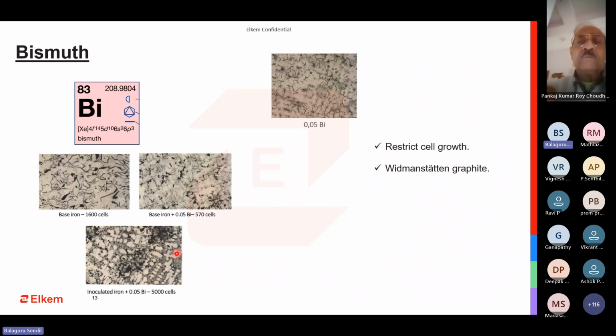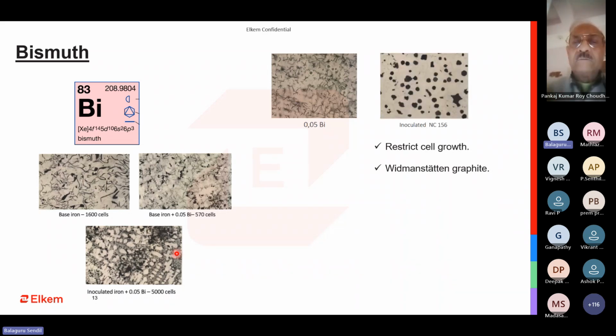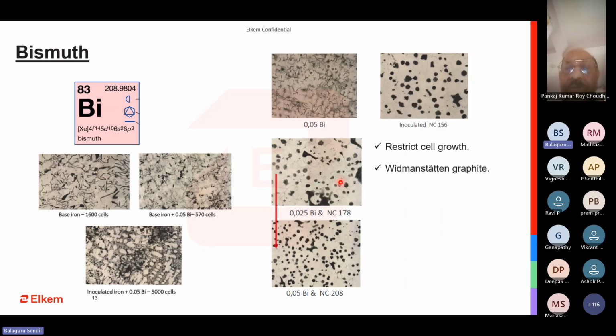But when it comes to ductile iron, this is what the bismuth microstructure looks like. After having 0.05 bismuth, it is not a very great microstructure. But when I inoculate it, I achieve this. But the advantage of bismuth is that, if you can see here, the nodule count has improved from 156 to 178 with inclusion of 0.025 bismuth. When I double the bismuth to about 0.05, I see almost a drastic jump in the nodule count.